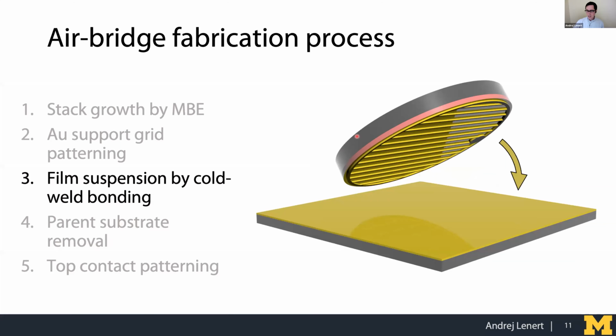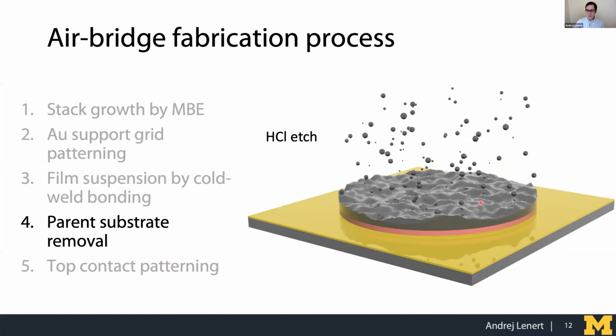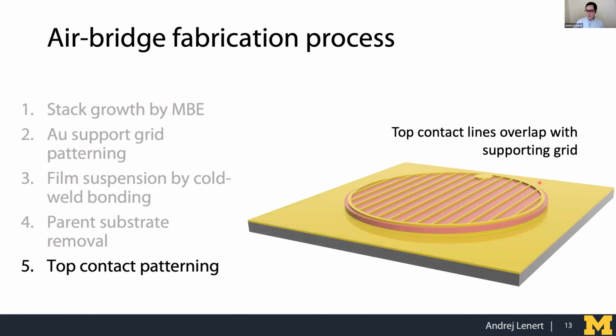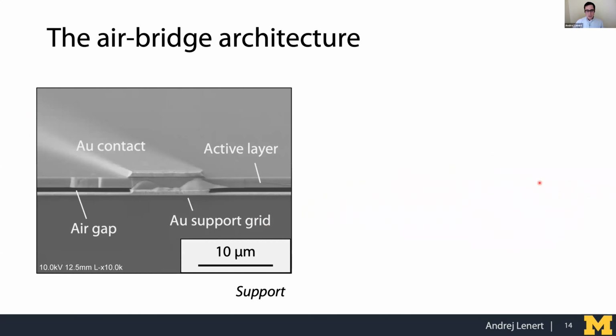Then that wafer is flipped over and bonded to a planar gold mirror. And once that bond is established, we can etch away the parent substrate, the indium phosphide substrate that was used to grow the epi film. And then we can pattern out the cell and put a top contact. And the resulting architecture is shown here.